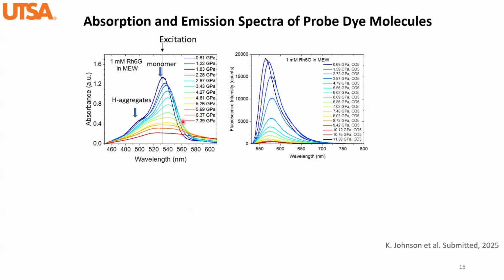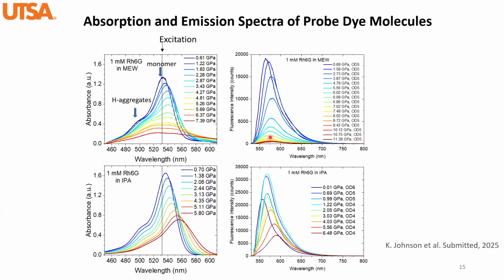And in the case of fluorescence, we have the reduced fluorescence intensity overall, and also a very complicated peak shift. You can identify here that there is a red shift first at lower pressures, and then as pressure keeps increasing, it became a blue shift. And also, we were trying to see if different solvents will give us different results. It seems yes, because from the absorption spectrum of rhodamine 6G in IPA, we have seen that there is a reduced relative absorption of the H aggregates over monomer, actually. And also the monomer sees a constant redshift in this case.